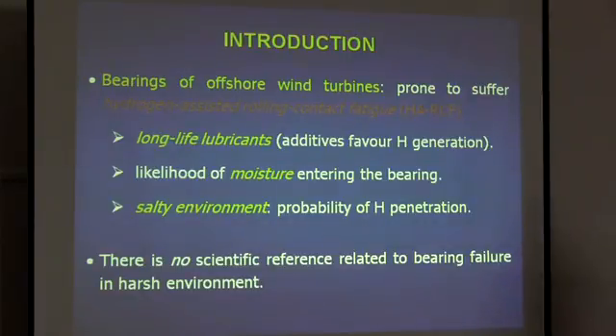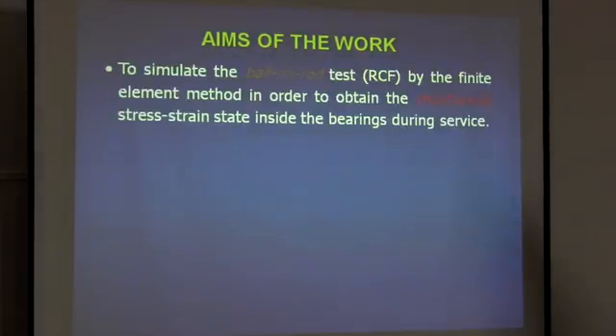But the companies, for instance SKF in the Netherlands, apparently this research was performed in the framework of the MultiHy European project, a multi-scale approach to hydrogen embrittlement of crystalline materials. One of the industrial partners was SKF in the Netherlands, who manufactures this bearing for wind turbines. And they have problems because of premature failure of this bearing due to, supposedly, hydrogen-assisted cracking and rolling contact fatigue.